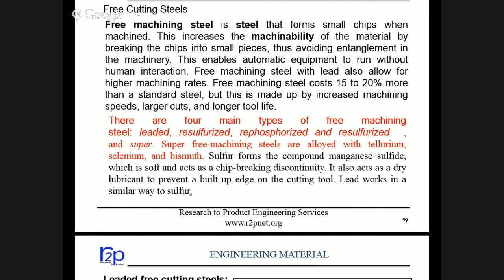They can be zinc plated or yellow passivation, electrodeposition can be done, but no heat treatment is required in such cases. So there we specify free cutting steel, where the production rate may be some 10,000 per day. So they are made on high speed, high productivity machines. There are 4 main types of free machining steel, where lead is added, or sulfur is added, or phosphorus is added, and there are some super free machining steels with some microalloying elements: tellurium, selenium, and bismuth.